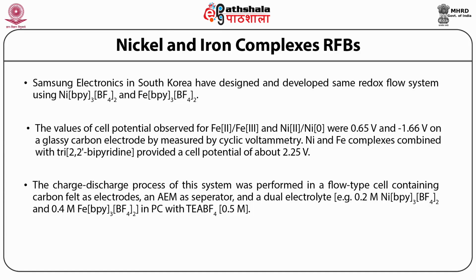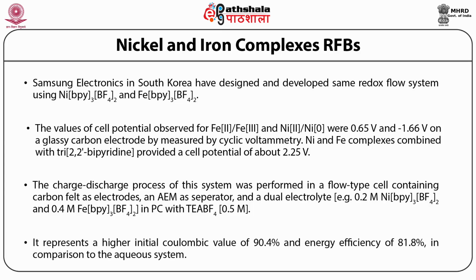For example, 0.2 molar Ni(bpy)3(BF4)2 and 0.4 molar Fe(bpy)3(BF4)2 in PC with 0.5 molar TEA BF4. It represents a higher initial coulombic efficiency of 90.4% and energy efficiency of 81.8% in comparison to the aqueous system.